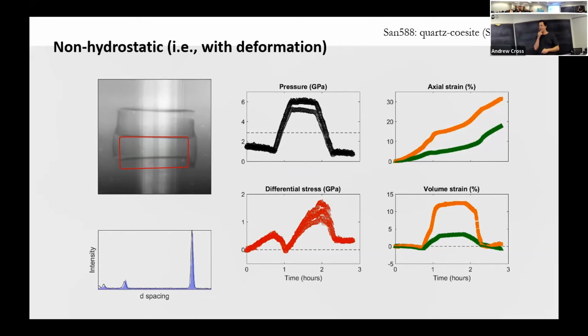And what's really interesting here is as it goes through the phase transition, then the olivine load cell, which has pretty much just been going at a constant rate, starts deforming much quicker. So we think what's happening here is that the quartz is trying to expand this way, but it's pushing up and loading up the olivine sample stacked below it. And so the olivine starts to yield and deform a bit faster.